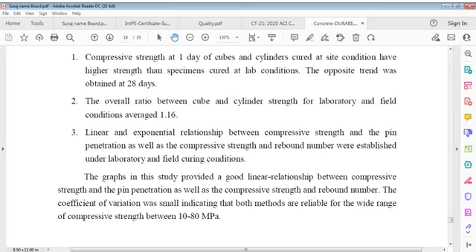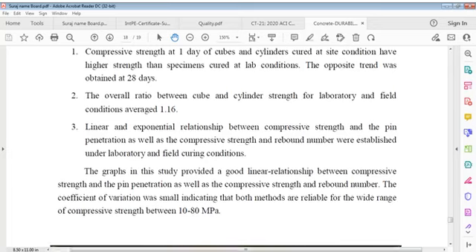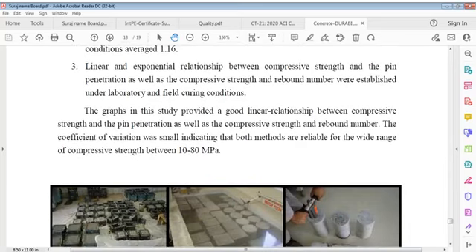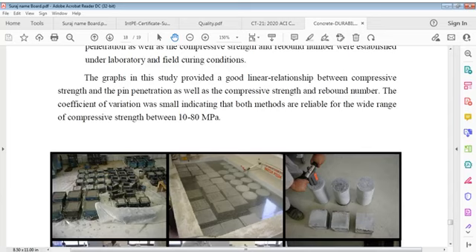Linear and exponential relationships between compressive strength and pin penetration, as well as compressive strength and rebound number, were established under laboratory and field curing conditions. Graphs in this study provided a good linear relationship. The coefficient of variation was small, indicating that both methods are reliable for a wide range of compressive strength between 10 to 80 MPa.